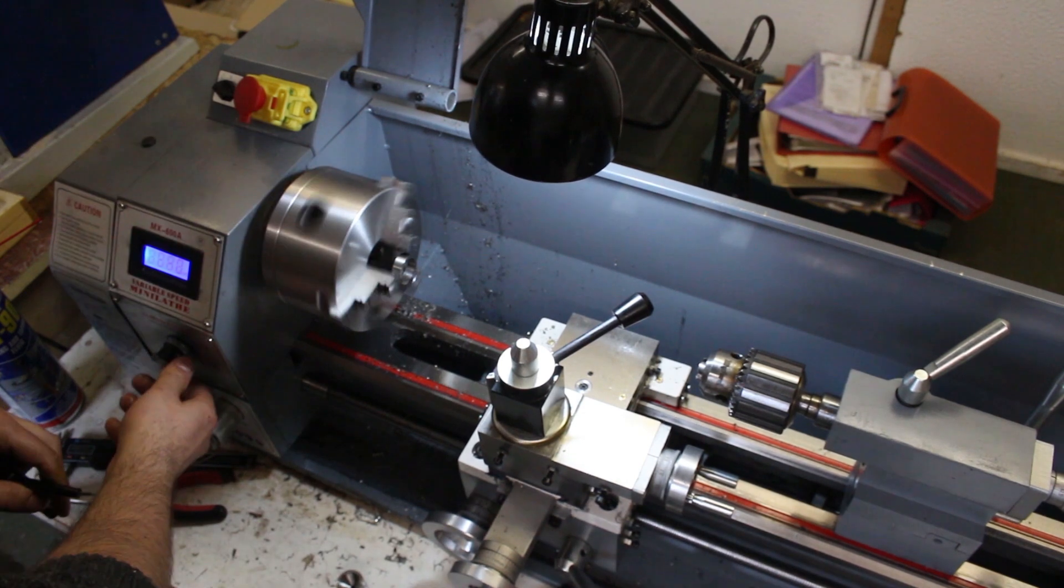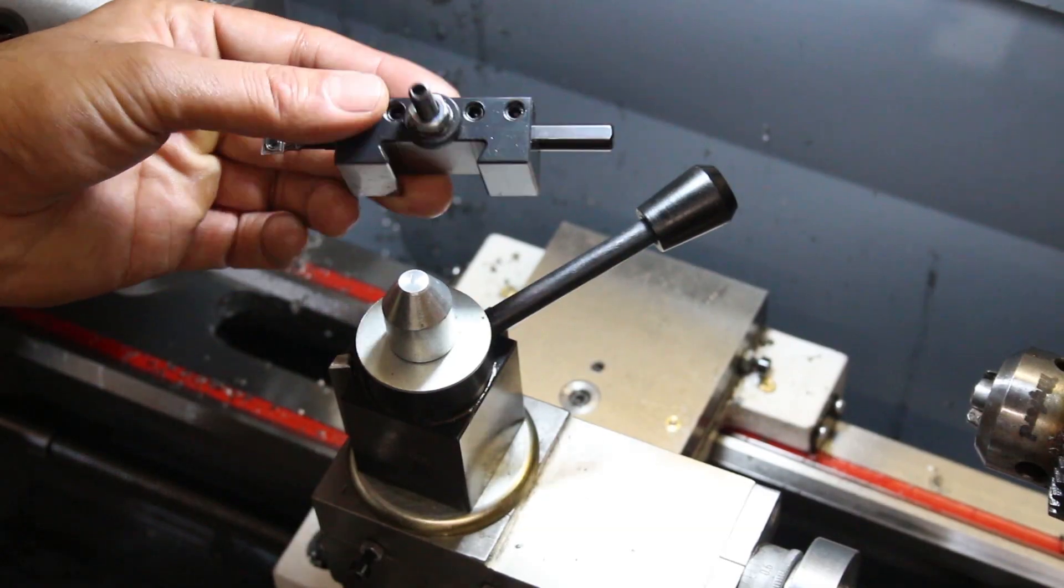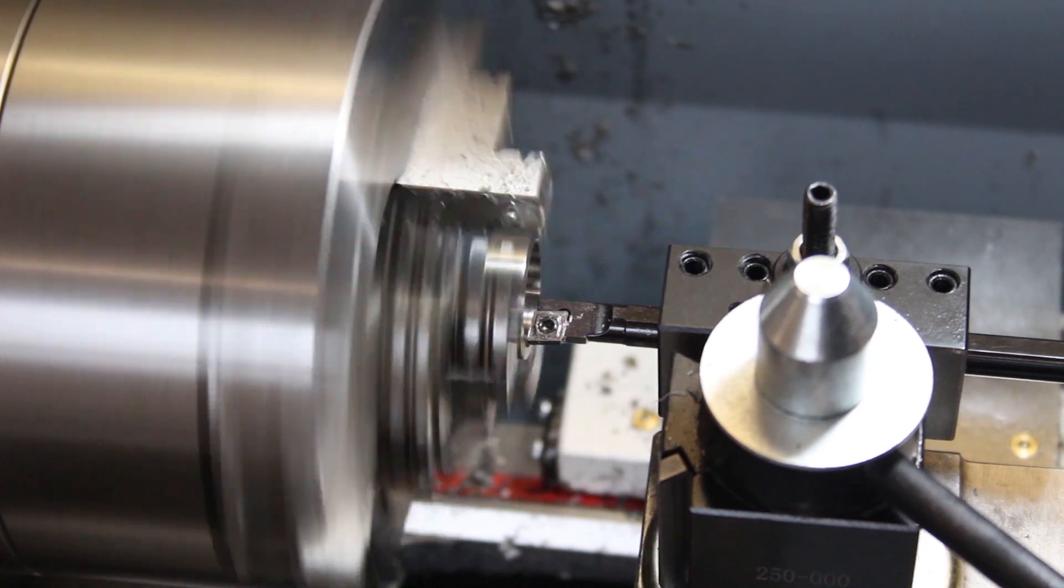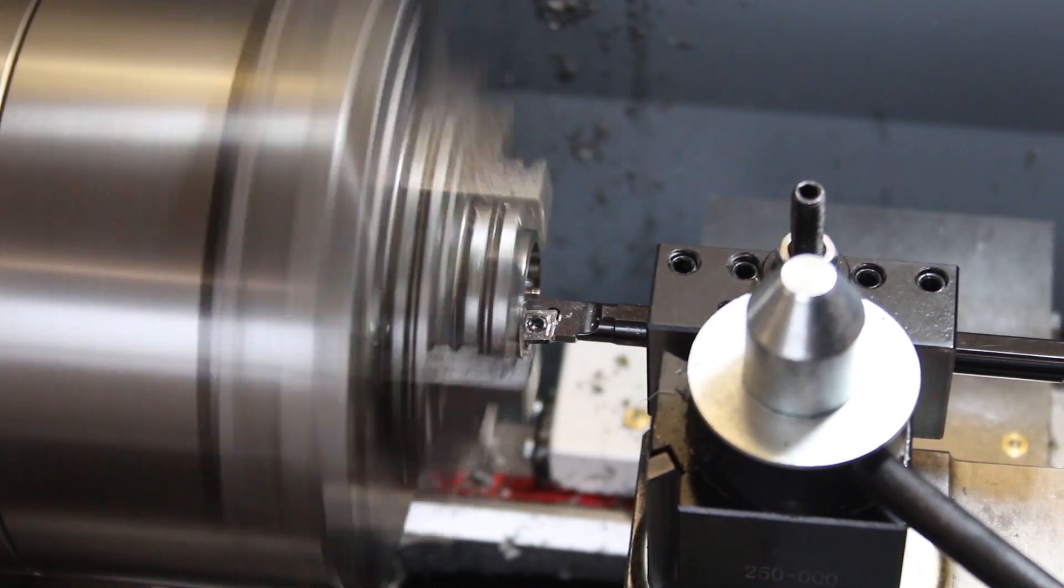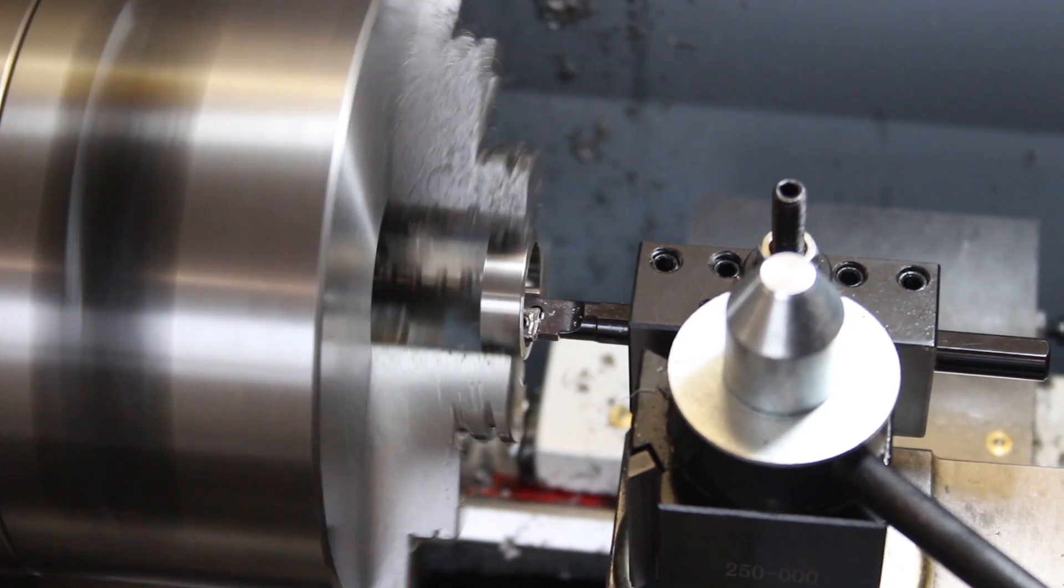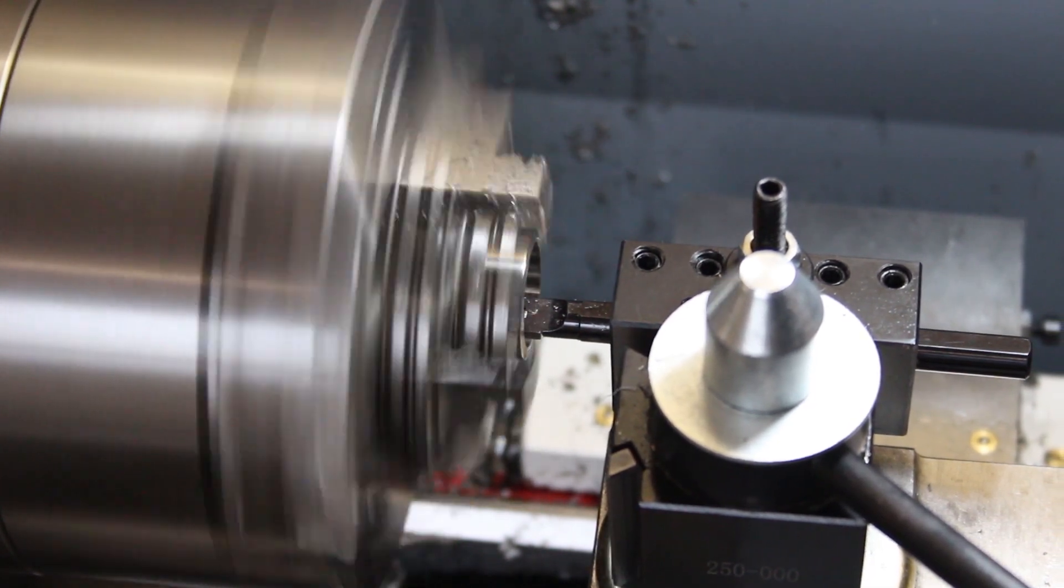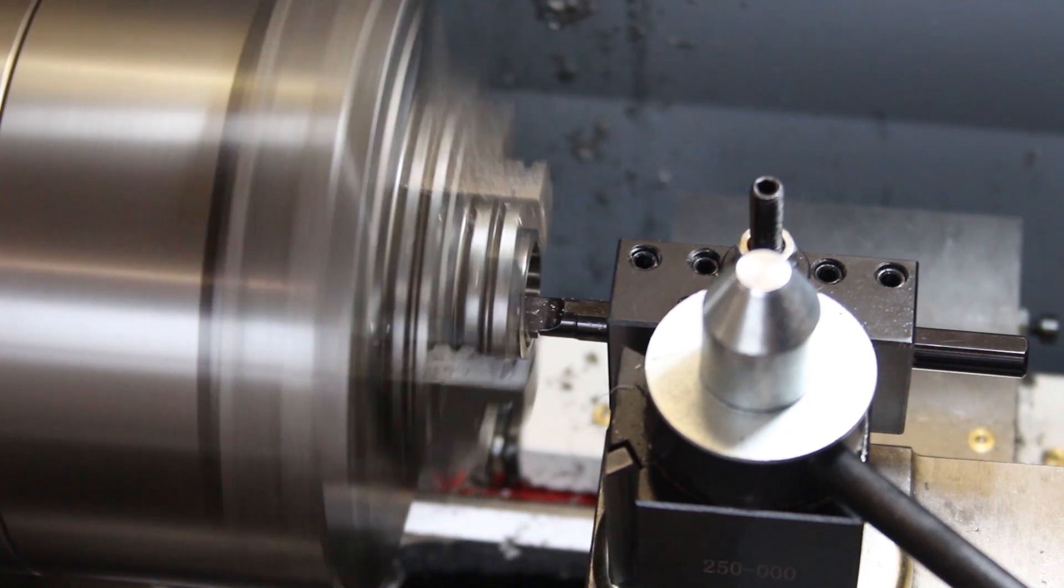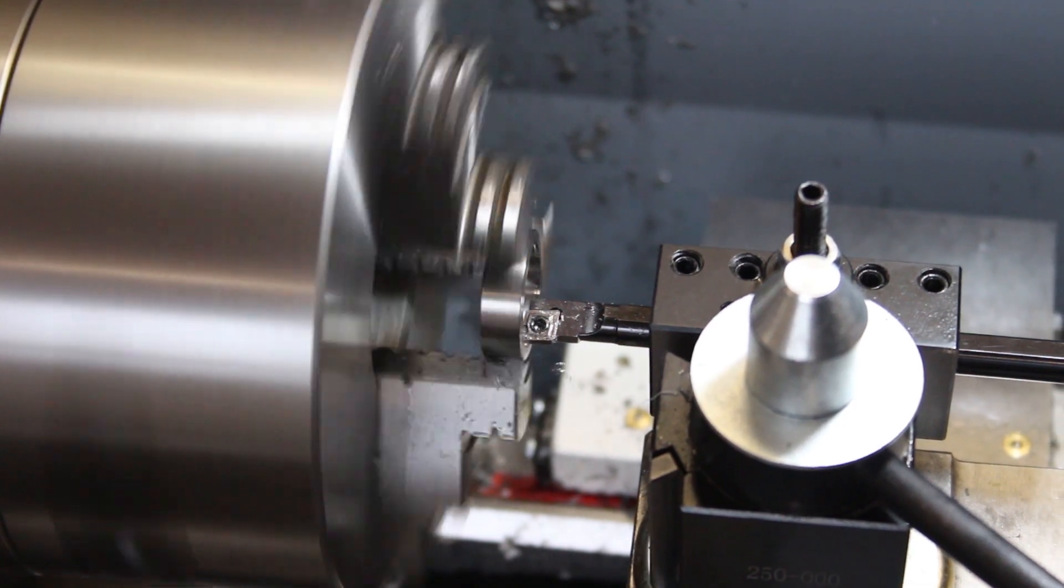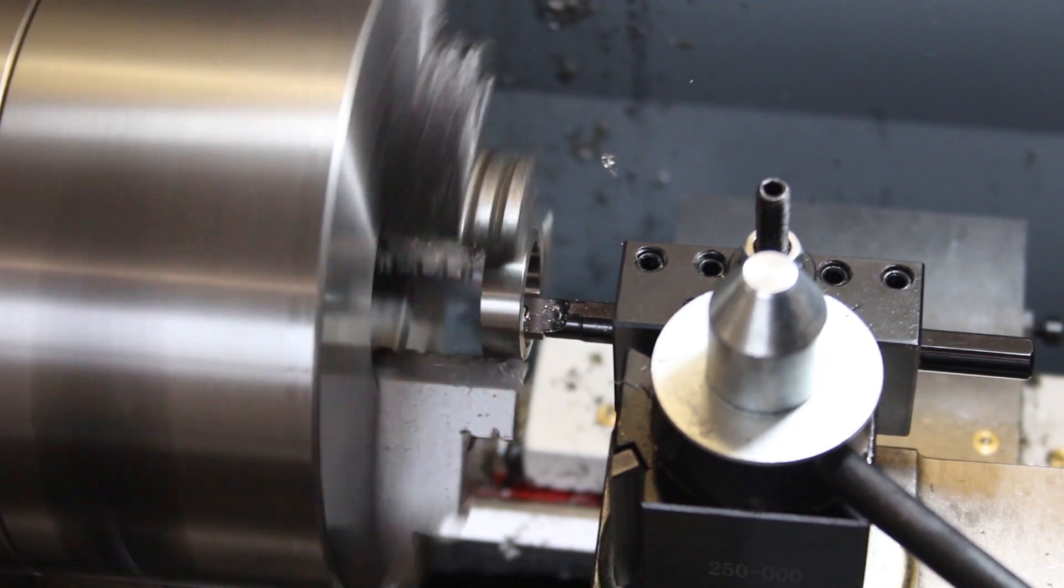I started out by using the boring tool. I found that using a relatively fast spindle speed of around 600 to 700 rpm and a slow feed rate with a sharp carbide cutting tool really leaves a nice finish on titanium or stainless steel. So I went through and did a few passes with the boring tool. I was never able to do this on my old lathe, so this is probably the most satisfying part of the process for me.